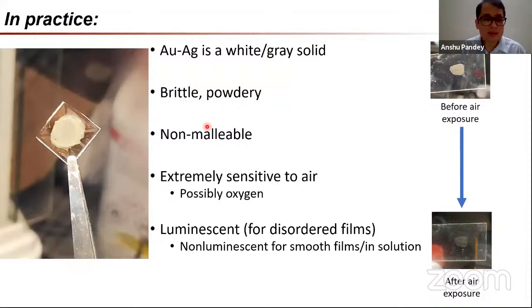Now, why would I write such a thing? Because in our early experiments, once we got hold of the first 100 mg of the material, which we knew was reasonably pure, we decided the simplest way forward might be to hammer this powder into a flat film and then try to use it. So we tried pressing it in a die, etc. And we quickly learned that this was quite unlike gold, which is the most malleable of materials. It's totally non-malleable. It's a very silly experiment to do, but very instructive in some sense. It was in fact very brittle.